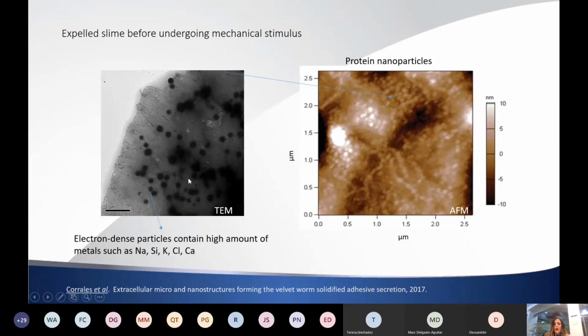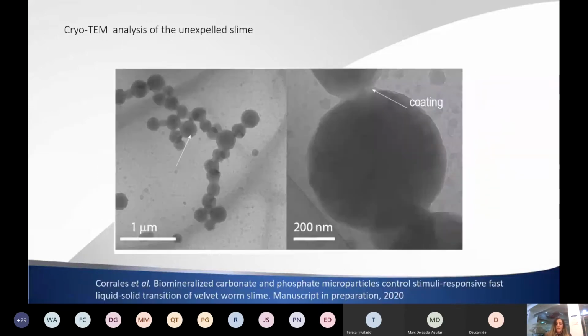But we were interested not in the protein matrix, that it has proteins, other lipids, carbohydrates. We were interested in why a material like this has already these microstructures in the slime, and why these microstructures disappear. Maybe, we thought in that moment, it could be correlated to this fast drying process. So first of all, when you have a material like this, you cannot do much, and you see these particles, because it could be a drying artifact. You can have a liquid, and when it dries, salts precipitate, and it could be an artifact.